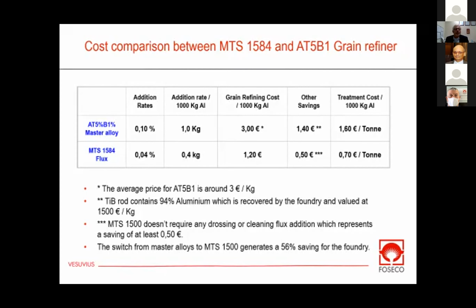So for those foundries, there's two advantages. One is a finer grain and better mechanical properties, and the other is a cost reduction because of the reduction in flux compared to master alloys. Foundries using this process have completely stopped using the Tibor master alloy, so this is a significant saving for the foundry in terms of purchasing.